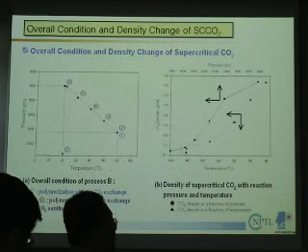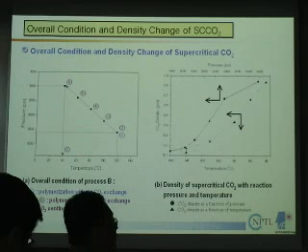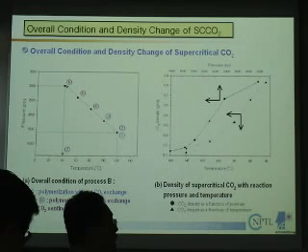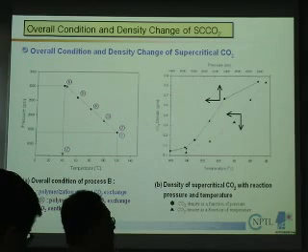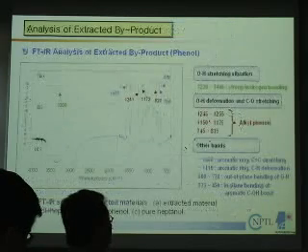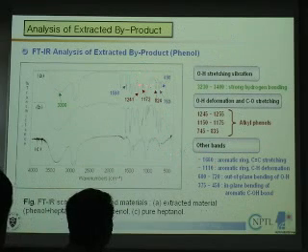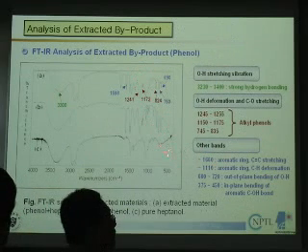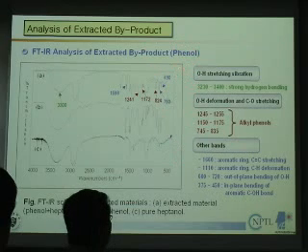So we chose three different processes to verify our concept. The first is dispersion polymerization without an exchange process. The second process is a partial extraction process. The third process is the continuous exchange process. So this one tests whether we can actually extract this byproduct from the growing particles.